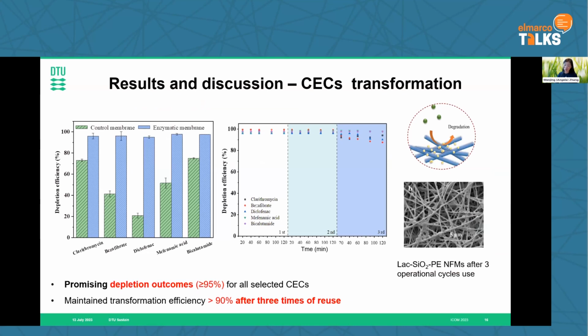Then we put it to the test. We put in the filtration with contaminants, those CECs, like diclofenac, those kinds of pharmaceutical compounds we frequently find in our water in Denmark. And then we do the analysis. When we pass that water through, we found the depletion efficiency of those nanofiber membranes can reach up to 95%. So 95% of those compounds can be removed and degraded. And also we operate for 3 cycles.